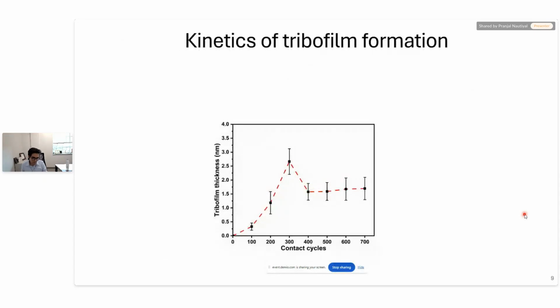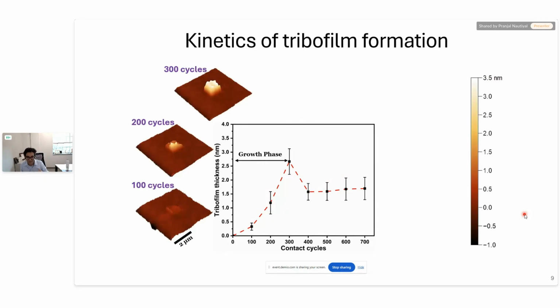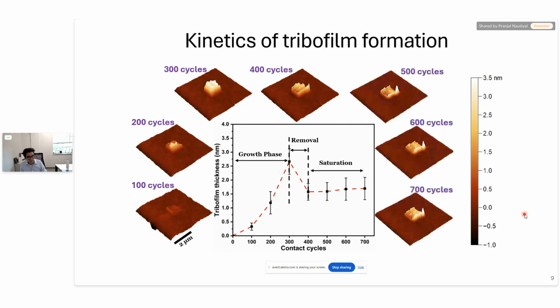Because AFM provides great sub-nanometer depth resolution, we can quantify the formation of this film with good precision. So here I'm showing you the thickness evolution of tribofilm as a function of contact cycles. Within 100 cycles, we clearly saw the growth of the film. And as we continued sliding cycles, the thickness of the film increased. Thereafter, there was a slight removal of tribofilm, from 300 to 400 cycles. And then after that, the film thickness reached a steady state or saturation, and there was no further change in